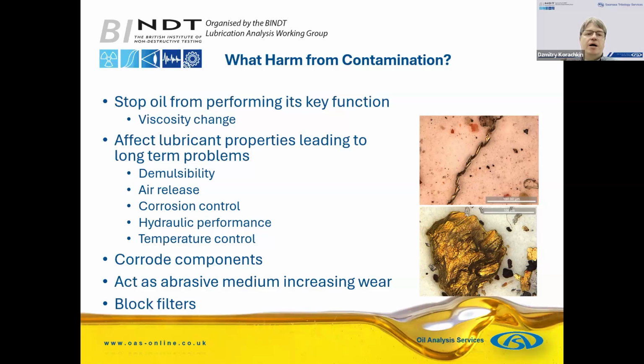Many contaminants are actually affecting the fluid, the bulk of the fluid. You can have fuel ingress, water ingress, ingress of a different lubricant with a different viscosity grade, and that can lead to a change in viscosity, and it can stop the lubricant from performing its key function. And there are other functions that can be affected, things like demulsibility, the ability for lubricant to separate from water, air release. There'll be issues with corrosion control, hydraulic performance, temperature control.